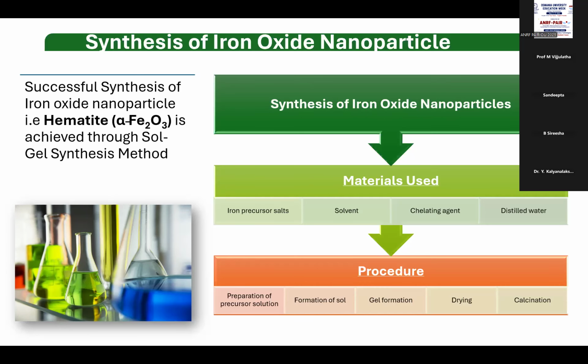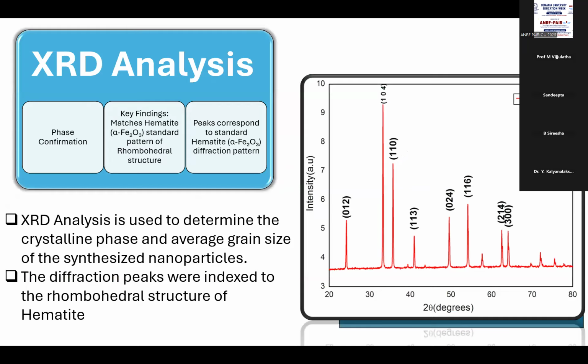In order to determine whether any other impurities are present in the material, and whether it has the hematite phase, XRD measurements were carried out, and here good crystalline nano-sized particles are formed. The diffraction peaks were indexed to alpha Fe2O3, which belongs to the rhombohedral structure. So we have confirmed the phase, and it possesses the alpha hematite phase.